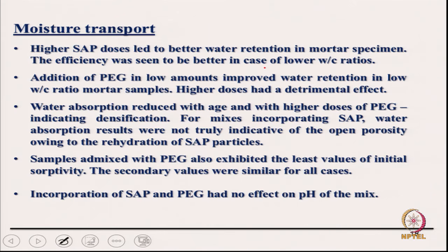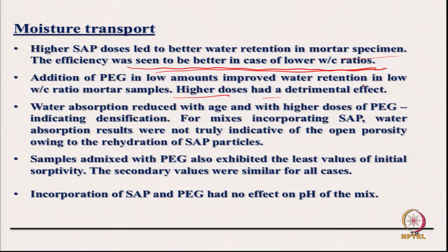Similarly, moisture transport, if you look at it, because durability issues are there. Higher SAP doses lead to better water retention, and mortar specimen efficiency is better at lower water cement ratios. A low amount of PEG improves water retention at low water, and the same thing with high doses, as with strength we have seen. So, dosage has to be optimized. Water absorption reduced with age with higher doses of PEG, indicating densification. For mixes incorporating SAP, water absorption results were not truly indicative of open porosity owing to the rehydration of SAP particles.